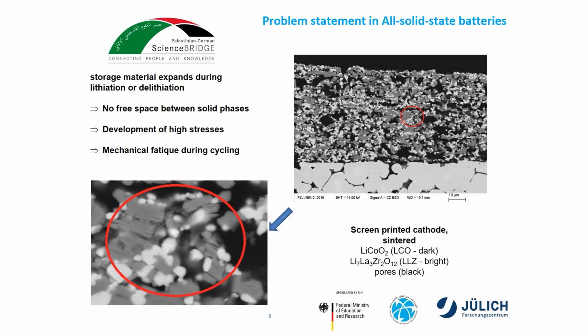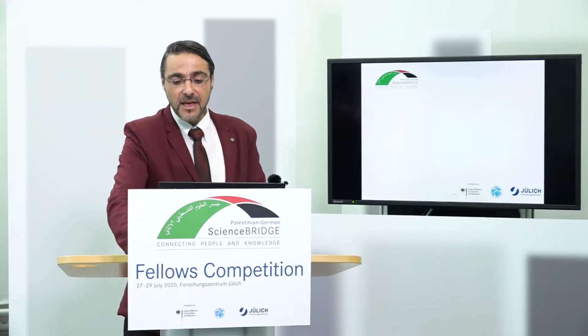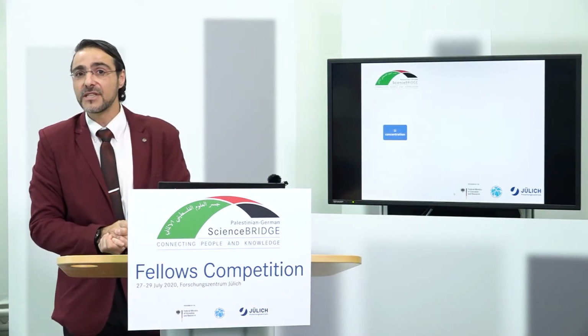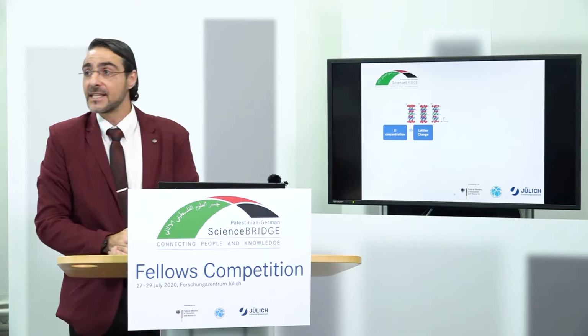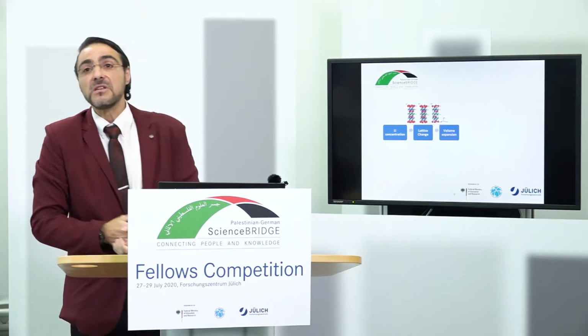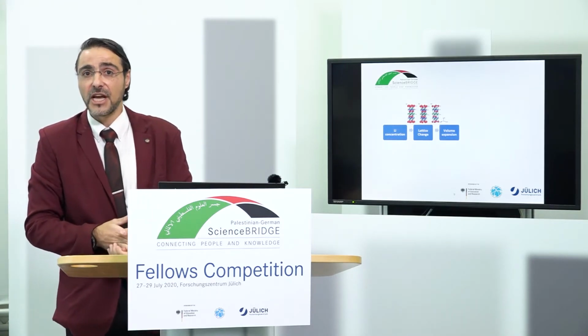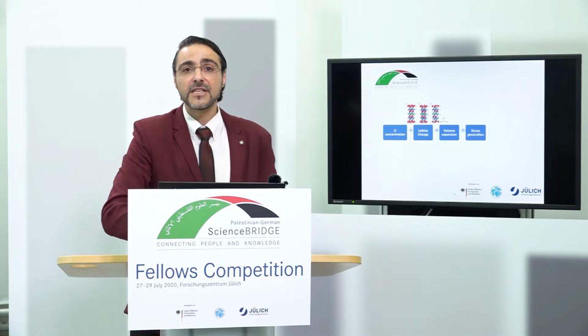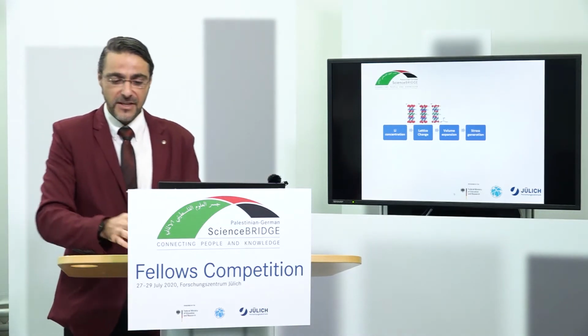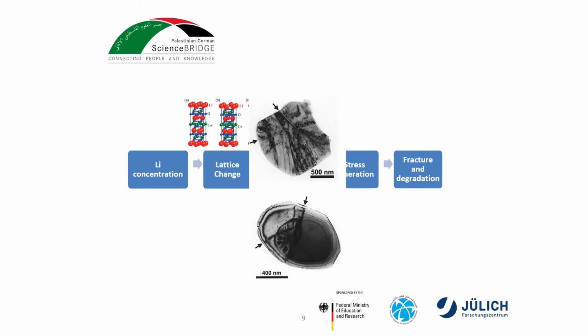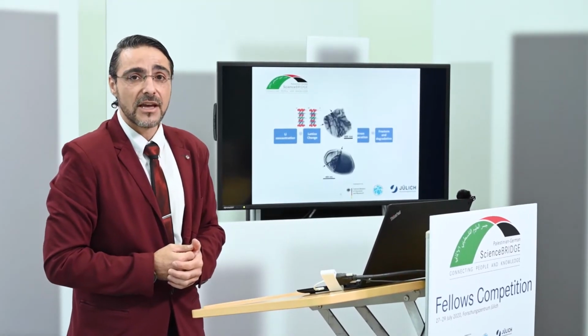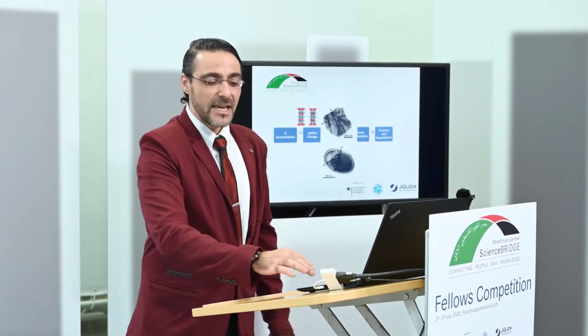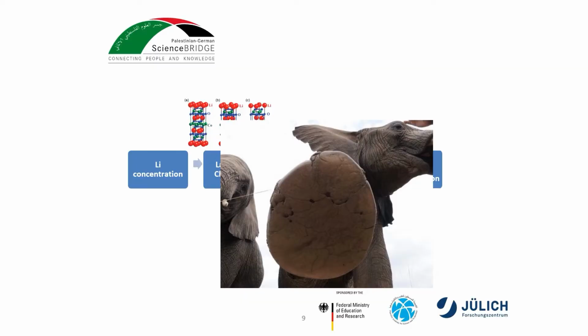So in brief, due to the lithium concentration, we have a lattice change, and then this yields a volume change, especially in the C direction, and this will generate a stress, and after that, this will create a fracture or degradation. This degradation we can see here in SEM images of lithium cobalt oxide, but we see it very often in the foot of elephants.